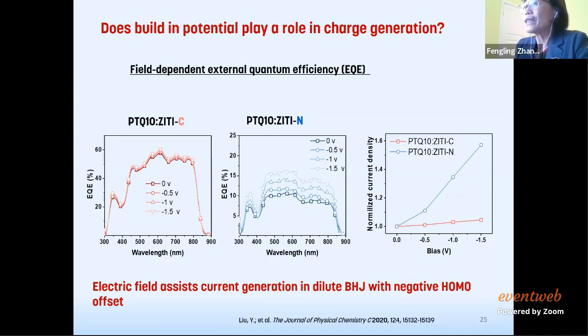So that means the built-in potential in the device assists the charge separation in the active layer with negative driving force. So if the driving force is large enough, then the built-in potential impact is not so significant. But when the driving force is negative, the energy offset doesn't help to separate the excitons. This built-in potential just steps in to take the role of separating the exciton into free charge carriers. So that's our work to identify the built-in potential's contribution to charge generation in the dilute bulk heterojunction.